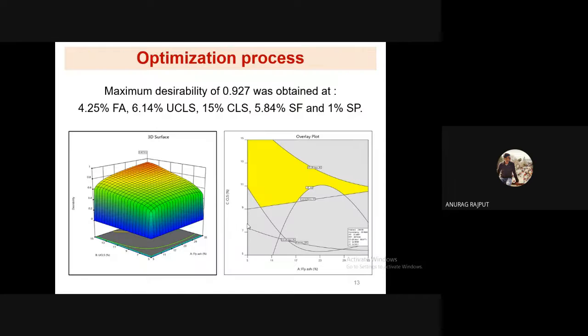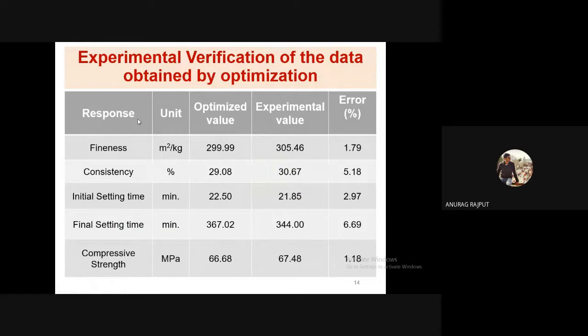So after having this mix, we did the experiment again. We performed the experiments again, and these are the optimized values obtained from the results. And these are the experimental values from the experiments I performed, and they are very near to the optimized values. So the error was very small.